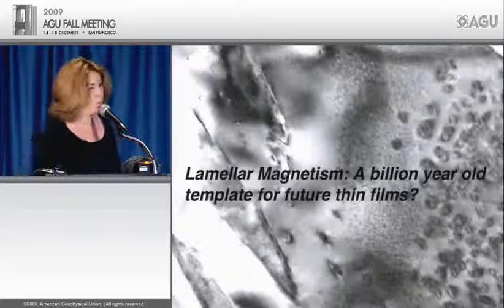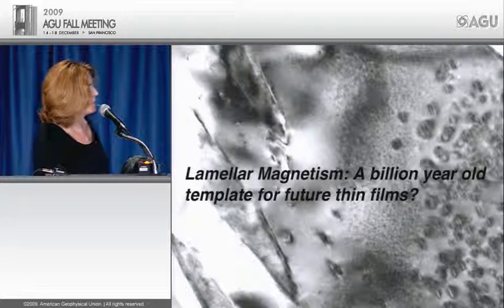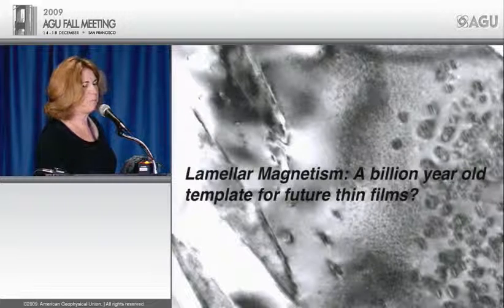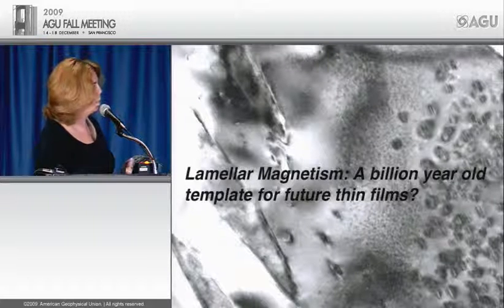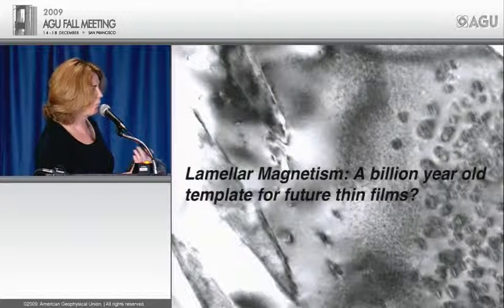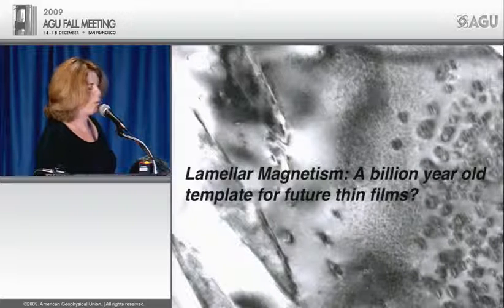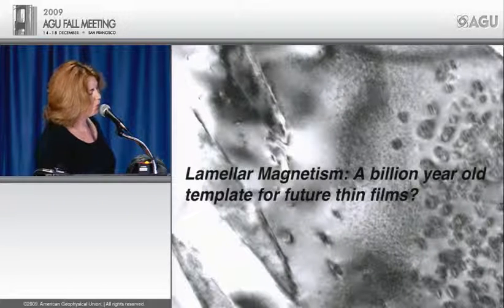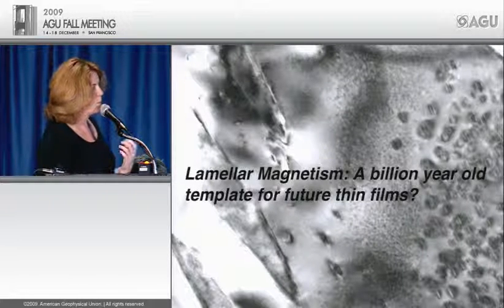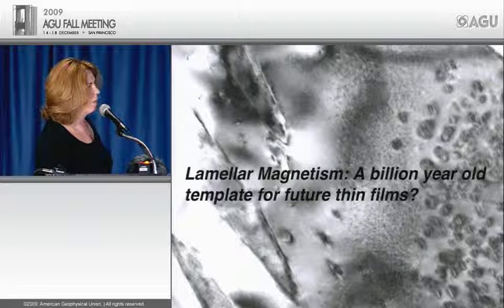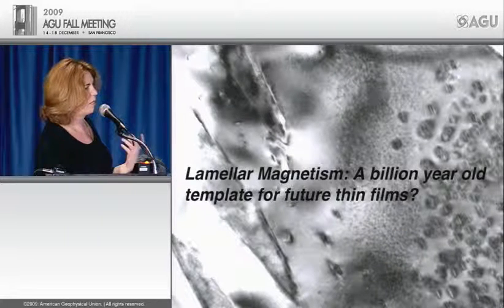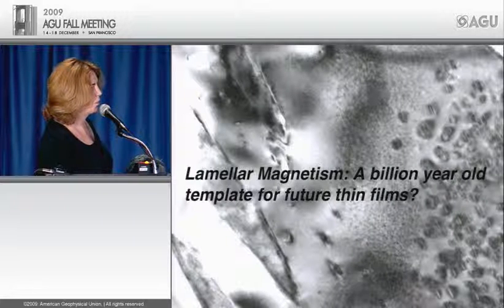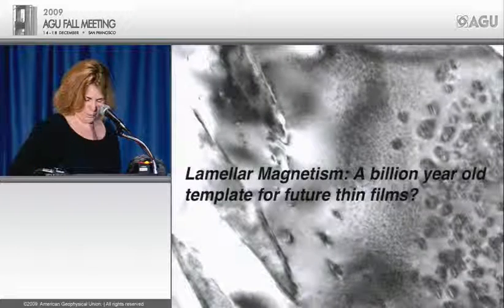So what we've been looking at, and I'll just spend the last 10 minutes to look at this, is materials which have an exchange coupled nature to them. They have, in one way or the other, a type of contact layer, type of defect moment on it. And they have very special properties. They're very high coercivity. They have very high temperature stability. And there's a lot of interest in this type of material, because you might need a one-time read device or something that could take a higher temperature for both defense and space applications. So understanding the nature of the magnetization could also become a template for future thin films.